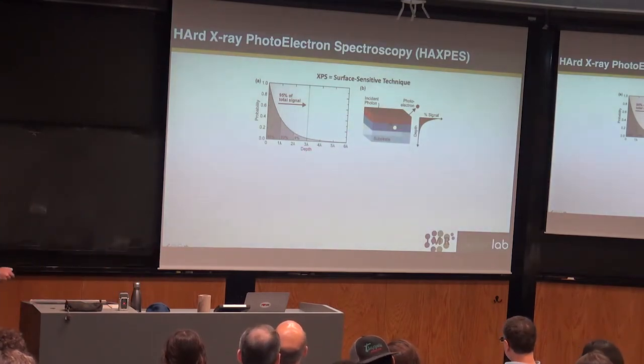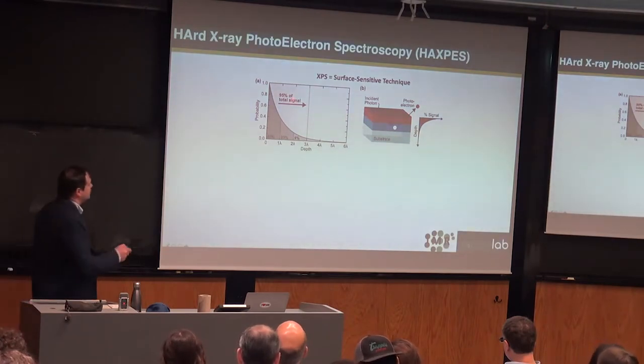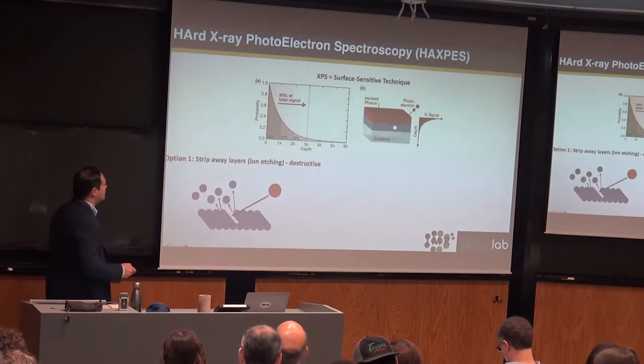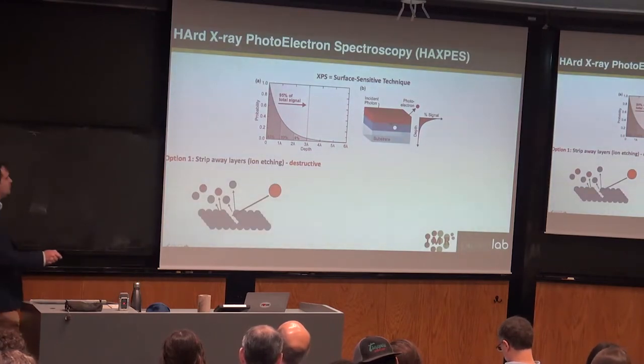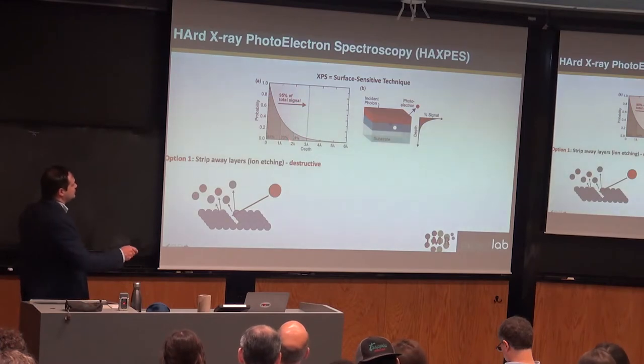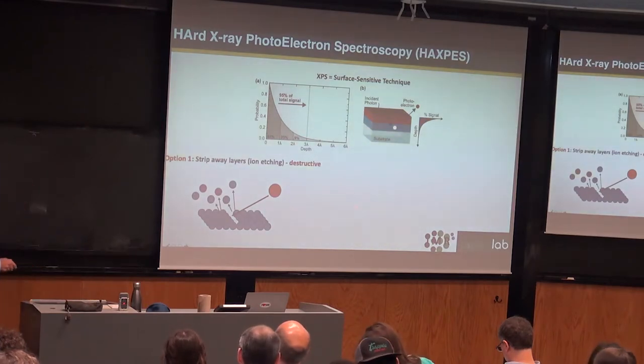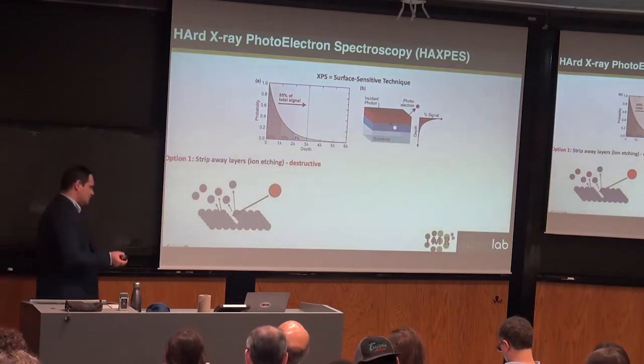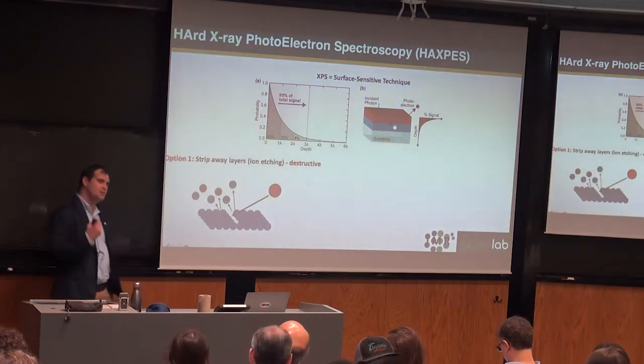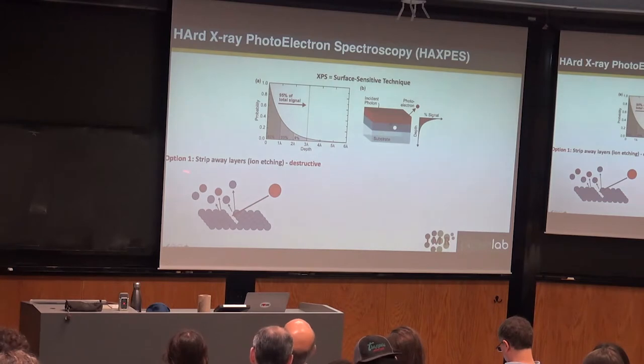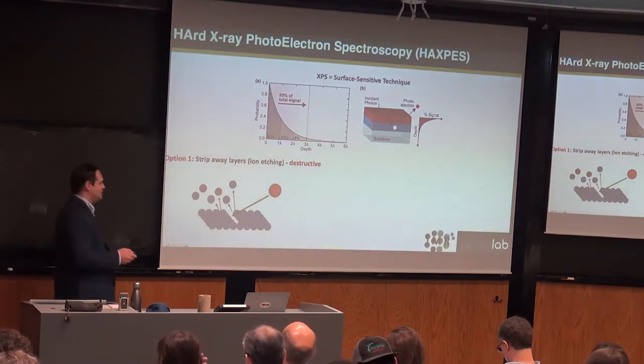But essentially it's a surface sensitive technique. The reason for that is because we're measuring the escaping photoelectrons, so we have this attenuation length. One trick is to strip away your layers, so you can get more information deeper by stripping away the top layers. But that's destructive. And if you're dealing with systems which have carefully controlled oxidation states, blasting them with ions will modify that precisely controlled oxidation state.